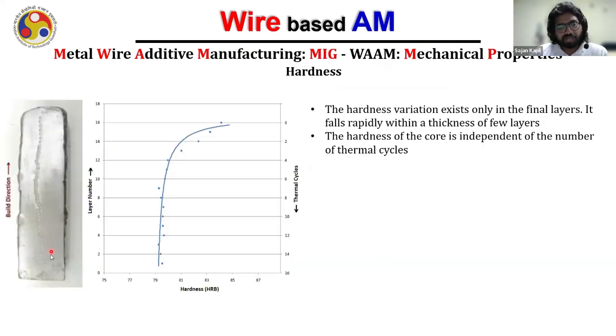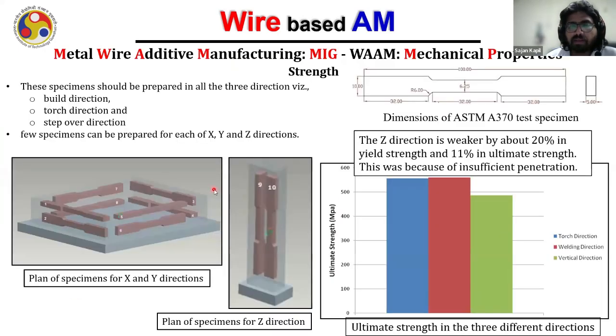This is a typical trend of hardness in parts created by WAAM, and you know that the hardness is high on top because fewer thermal cycles have happened here, but at the bottom, a lot of thermal cycles, heating, cooling, heating, cooling, heating, cooling, have happened many times. So the grains become coarser. They got merged with the neighbor grains also.